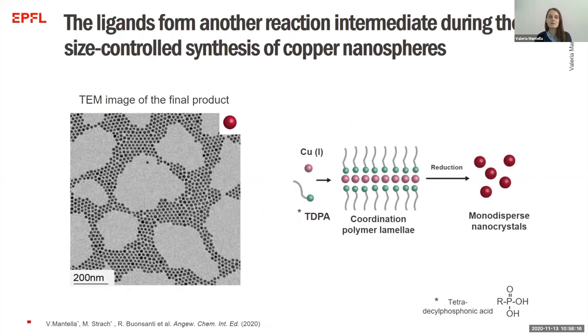And indeed, this is what we also observed during this time, the size-controlled synthesis of copper nanospheres, of monodispersed copper nanospheres, here shown by this TEM image. Now, in this case, what we found out is that tetradecylphosphonic acid, which is the ligand, is actually involved in the formation of a coordination polymer lamella along with the cuprous ions. And then these reaction intermediates undergo a reduction reaction to form monodispersed copper nanocrystals.